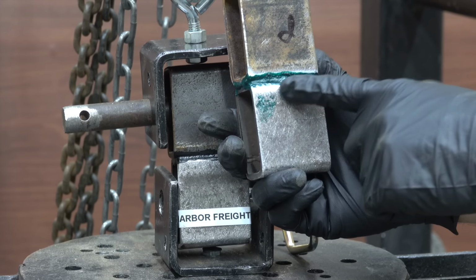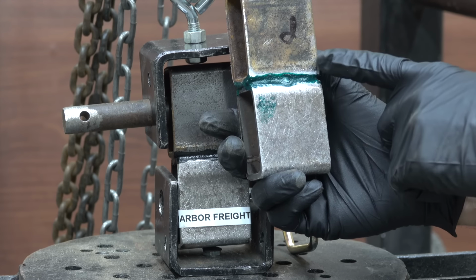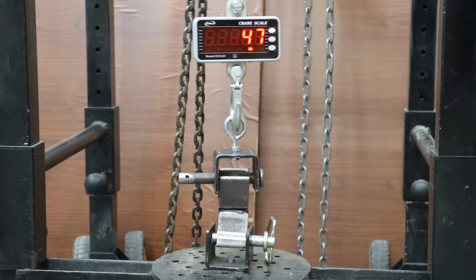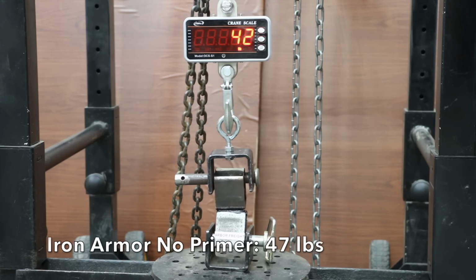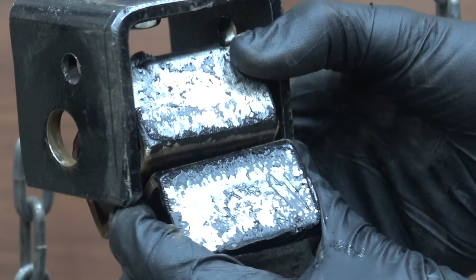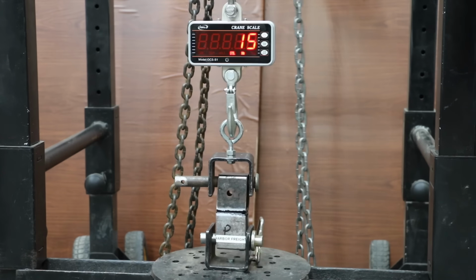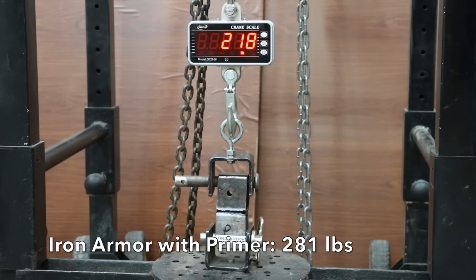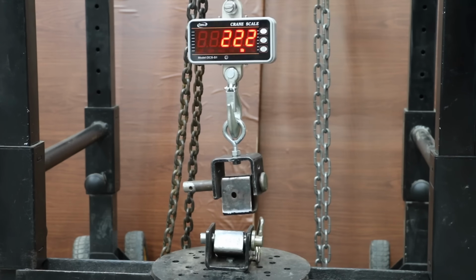In the next test, we'll see which products stick to primered as well as bare metal, beginning with Harbor Freight Iron Armor. Without primer, the Iron Armor just didn't bond well at only 47 pounds of tensile strength. The second sample was primered before the Iron Armor was applied, and it did much better at 281 pounds.